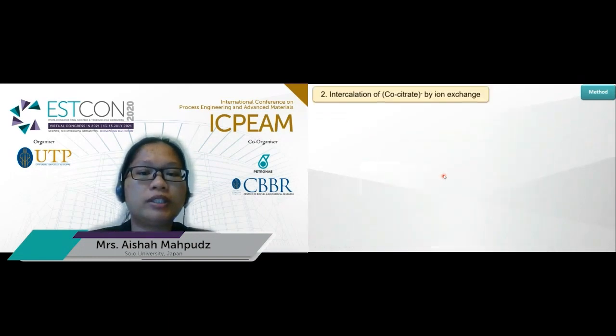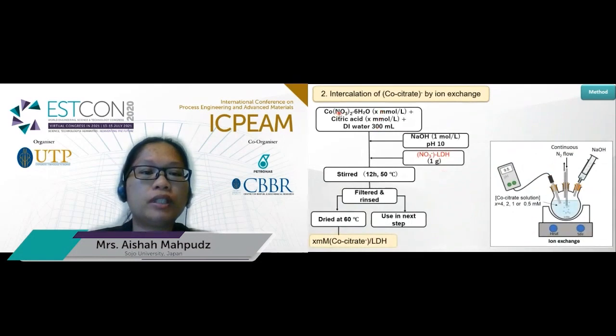For the intercalation of cobalt citrate, an equimolar ratio of cobalt nitrate and citric acid is added to 300 ml of water. Then sodium hydroxide is added to increase the pH to 10 before 1 gram of powdered nitrate LDH is added. This whole solution is stirred for 12 hours at 50 degrees Celsius, then filtered and rinsed. Half of it is dried at 60 degrees Celsius, and I refer to this sample as X millimolar cobalt citrate LDH, where X refers to the various concentrations of cobalt citrate solution used for preparing the sample, that is 4, 2, 1, and 0.5 millimolar. And half of the other solid collected is used in the reduction step.